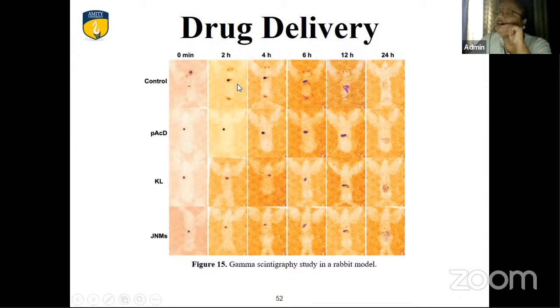But in case of the control, the unaided drug had spread to the bladder, eyes, and brain regions, indicating ill-defined oral distribution of free 5-fluorouracil. At 4 hours post-administration, the intensity of free drug has substantially increased in these areas, indicating the distribution of the drug. The hydrogels, however, swelled only slightly after 4 hours, gradually moving towards the duodenum without releasing any drug.